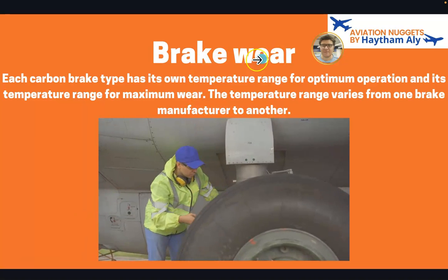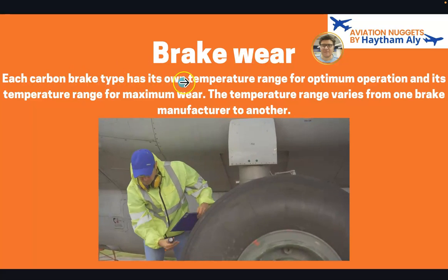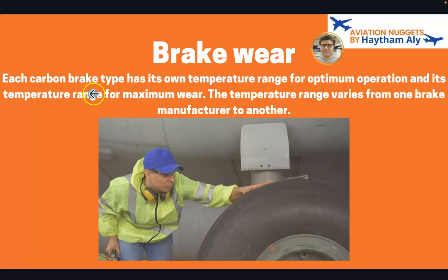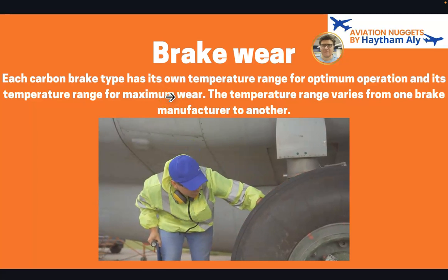So, brake wear. If we need to identify this phenomenon, each carbon brake type has its own temperature range for optimum operation and its temperature range for maximum wear. So, temperature also affects the brake wear rate. After landing and after applying the brake, the temperature of the brake unit increases, so pilots and aircraft maintenance people need to check the normal range of temperature of the brake unit before the next departure. And you need to check that the brake temperature is going down to the normal range before the next takeoff, as if the aircraft suffers a rejected takeoff, the brake unit must be prepared to absorb the high temperature that comes from the rejected takeoff.